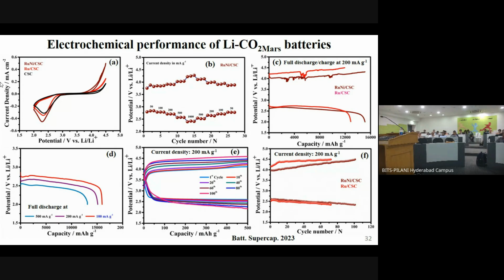Even for the higher current density, like 200 milliampere per gram, this is a comparison between the ruthenium candle soot and ruthenium nickel candle soot, and we can see that as compared to 72 cycles with respect to the ruthenium candle soot, ruthenium nickel candle soot gives you more than 100 cycles of charge and discharge.